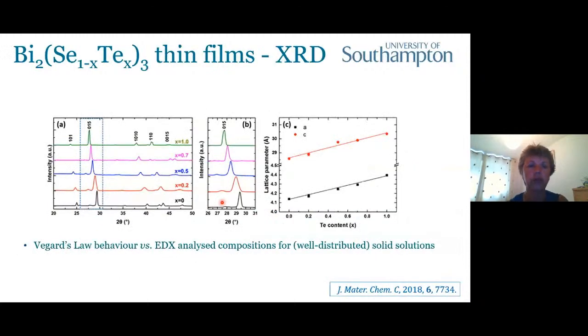And if we look at the diffraction data, and again, this was work that was done in collaboration with Dr. Chitra Gurnani, what we can see here is that we've got very nice solid solutions from the X-ray data. Instead of seeing separate phases from the mixed precursors going in, if we just focus on the 015 reflection, you can see that it moves smoothly with composition, which is a good indication that we have a well-distributed solid solution. What that means is that we've got the bismuth telluride structure, but we have some selenium sitting distributed through the lattice, sitting on the tellurium sites.